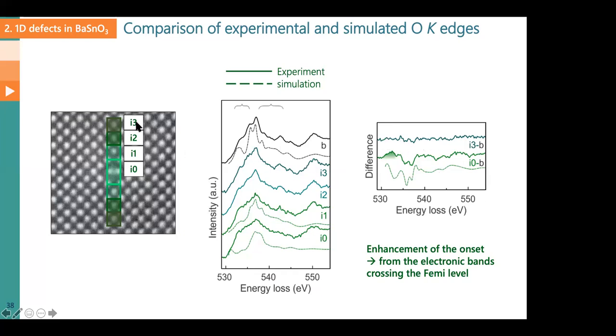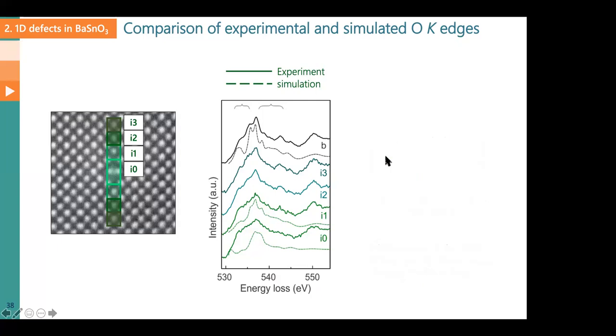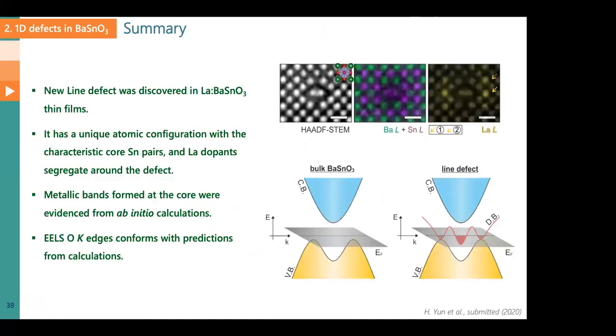But if I'm comparing the far away bulk material to the core of a defect, the difference is this here. And actually it matches perfectly what you would expect from the theory. The dashed line in the bottom is what the theory predicts. As my student will tell you, we got the money shot. It's a perfect match, and the prediction from theory that it should be metallic got completely confirmed. And the shaded region here is the region I was telling you about that has all of that metallic behavior.